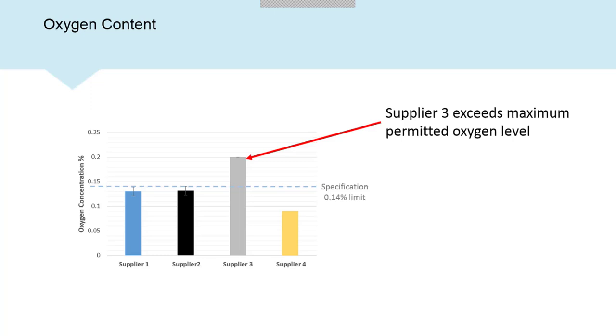In this case, we find that supplier 3 seems to have something more unique with that particular powder production method. Supplier 3 seems to be very much exceeding the oxygen limit. It is even on the limit of the standard grade titanium 6-4. So for AM purposes, this is much too high.